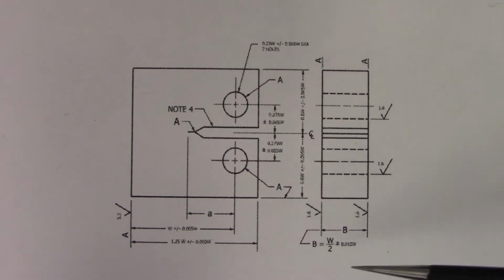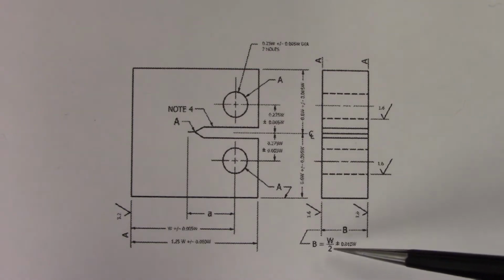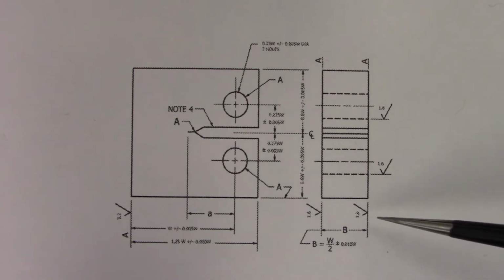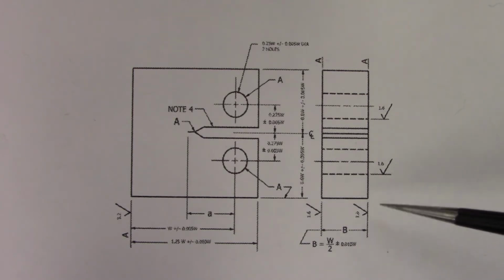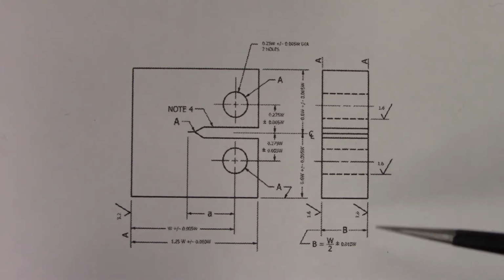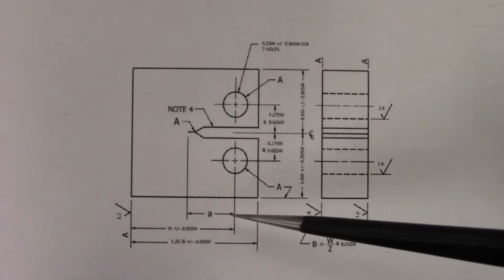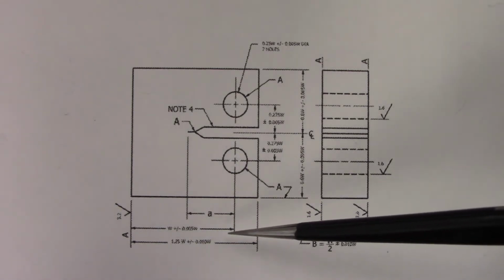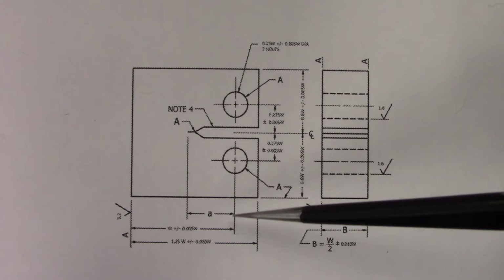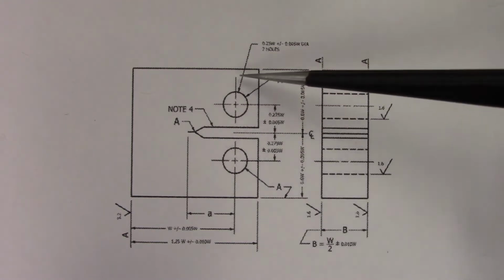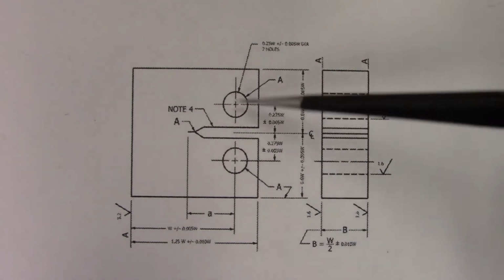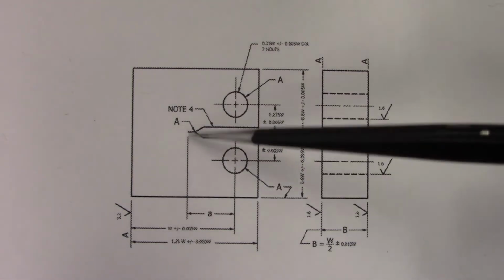Our B dimension here is recommended to be W over 2. But we can vary that. In our case, it's going to be closer to W over 4. For the plastics, it'll depend on the as-received thickness. And for the printed specimen, we wanted to save material, so we printed those to be 6 millimeters. The A dimension is a dimension that we're going to measure and record in this lab, and that's our crack length. The A dimension is measured, again, from the center line of the holes to the leading edge of the crack.